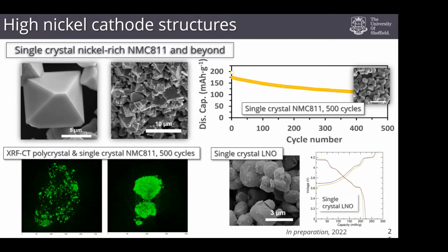So we've been looking at materials that have ever-increasing amounts of nickel that deliver ever-increasing capacities or energy densities. So you can see that for this particular material, this NMC 811, the ratio of nickel to cobalt to manganese is 8 to 1 to 1. Ideally, we would completely remove the cobalt. Cobalt is very expensive, it's very toxic. Most of it comes from the Democratic Republic of Congo, where there are no child labor laws, and there's huge ethical concerns about the mining practices for cobalt.